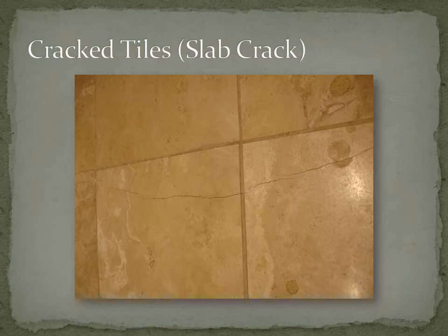Standard crack in the slab. You can tell that it's the slab and not the tile itself because it runs through several tiles. You'll see it go through the tile, and then typically it'll run over and follow a grout joint for a while, and then it'll take off through a few more tiles. I like to repair the crack with grout or epoxy rather than replacing the tiles. When you replace a tile, it'll always be a different color because it has patinaed over time, and it ends up looking a lot worse replacing the tile than it does just repairing the crack itself.